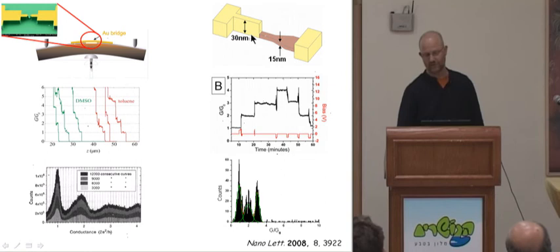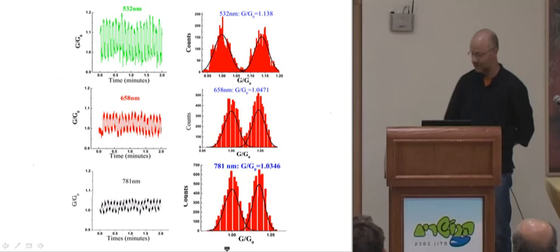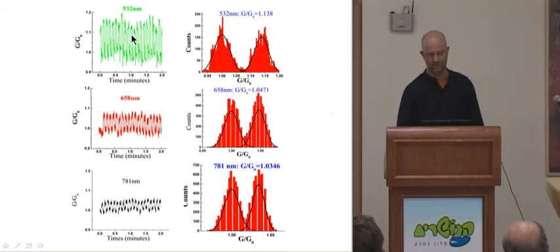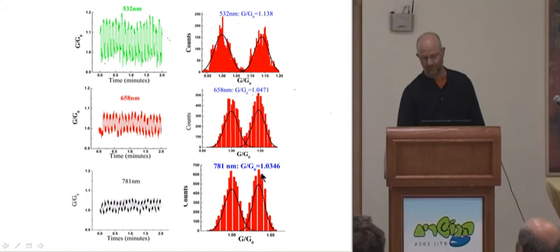The next step is to apply laser light on the structure and see what happens. All results shown here are from one gold contact. We applied green light and deliberately modulated the intensity at very low frequency to easily see changes as a function of light. We take the dark conductance — one histogram — and the under-light distribution — another histogram. We can do this for several wavelengths. There is a shift in the Gaussian from one value to a new average value, and the relative change is wavelength dependent.